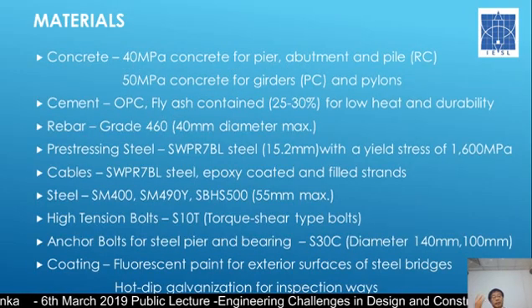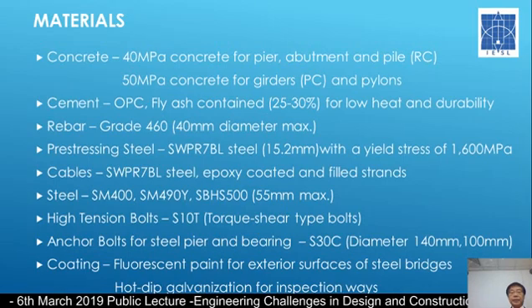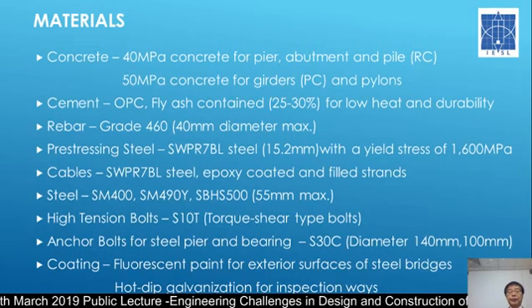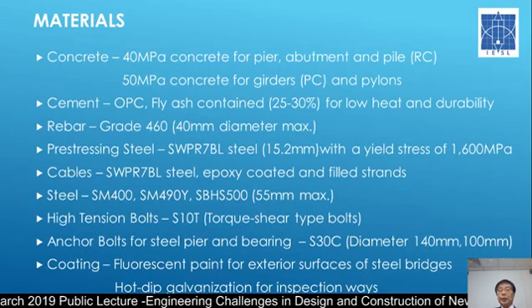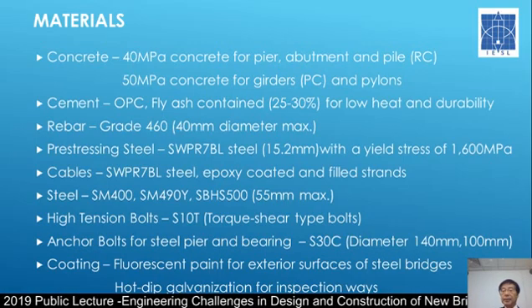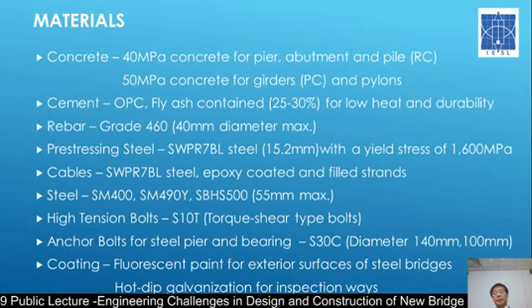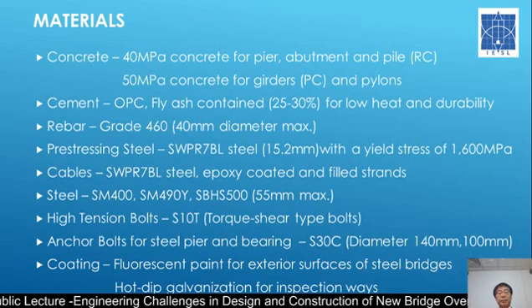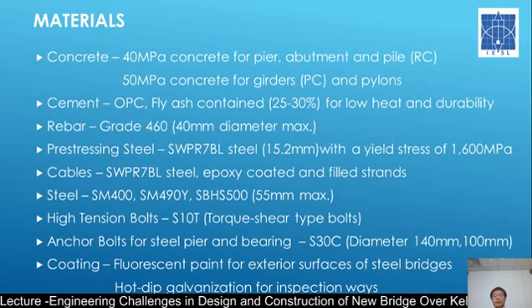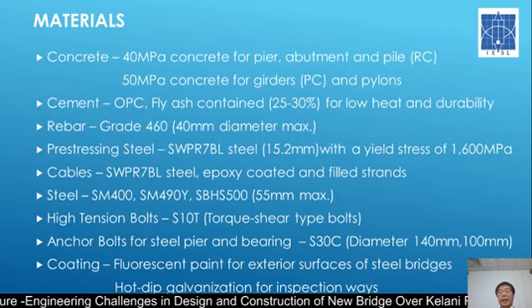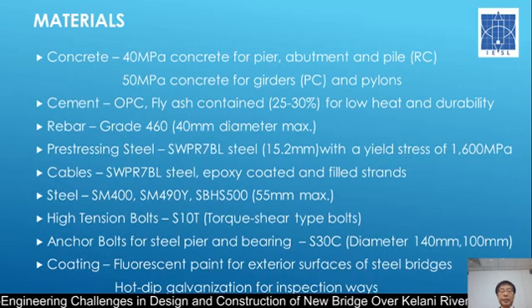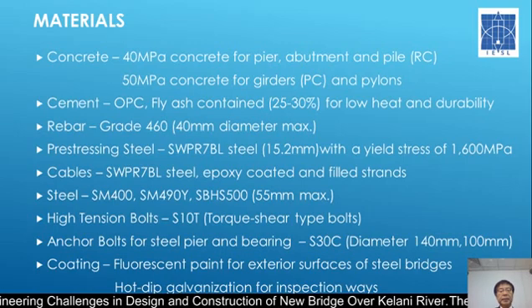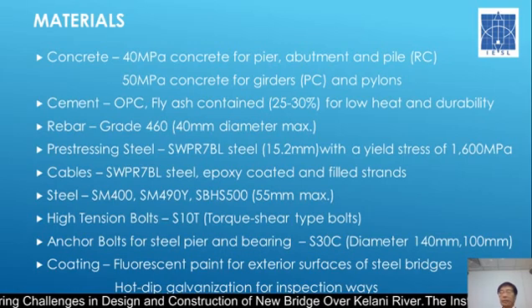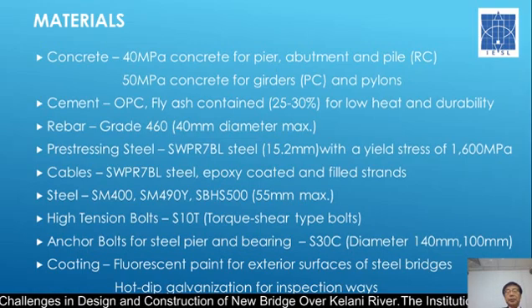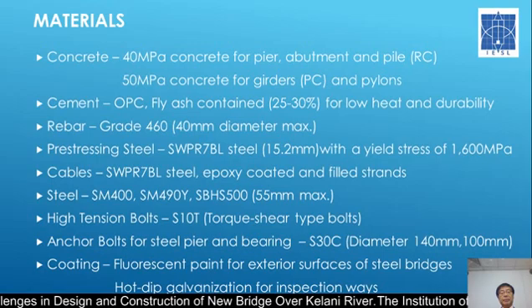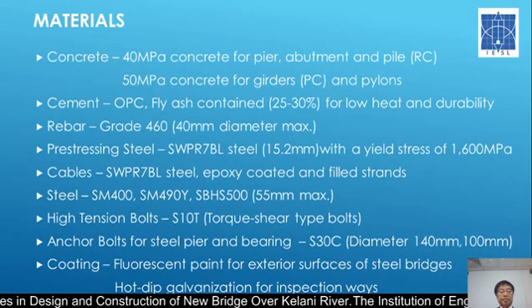Okay, now that we have finished the loads, I'm talking about the materials. Concrete: we have used up to 50 megapascal concrete, which is used for the PC pre-stressed post-tension girders as well as pylons, where the stresses are higher. But for the others, we use 40 megapascal concrete. For cement, we use fly ash contained cement, which is low heat and has long-term durability. But we also use OPC, ordinary Portland cement, for the superstructure.